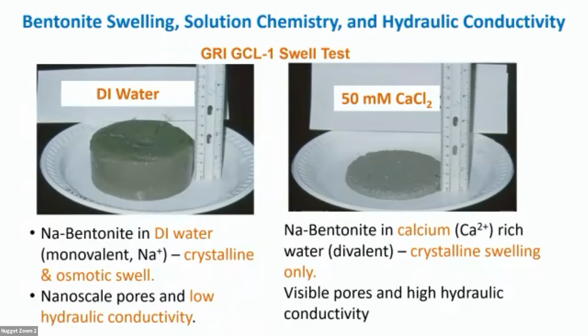Just change the geochemistry. And it's actually not a very concentrated solution, but a divalent solution. Same amount of bentonite, same mass per area. This is what it looks like. You can see if you look closely, if you've got really good eyes, that the granules of bentonite are still present. Their swelling is completely suppressed. This material is impermeable. This material is highly permeable. So just changing the geochemistry, we can have a GCL that's very impermeable or very permeable, depending on the situation.